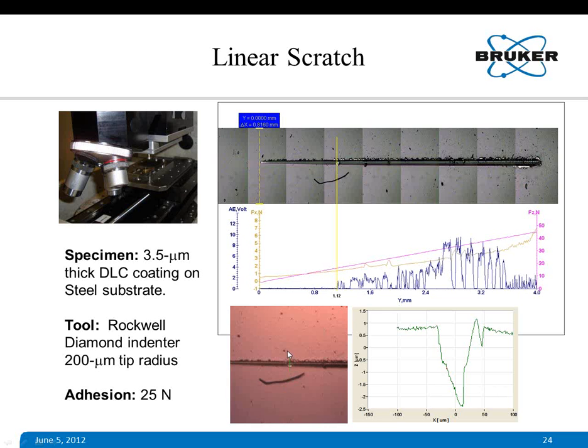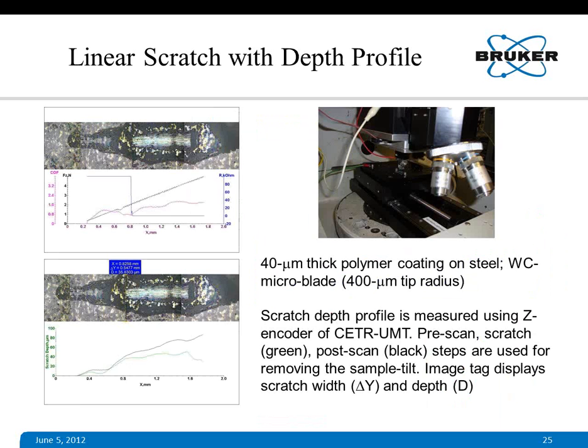At the point of failure, we did a profile of the scratch, and you see the profile here, which shows about 3.5 micron depth of the coating. Here is another example of a progressive scratch test with depth profile. This was done on a relatively thick coating, 40 micron thick polymer coating on steel, soft coating on steel.